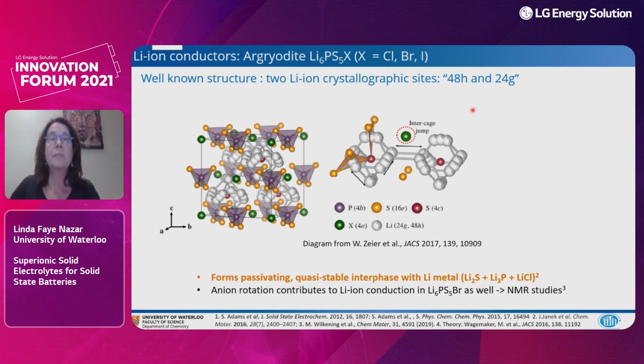And this is a nice cubic structure with PS4 tetrahedra and 2 lithium-ion crystallographic sites, which are known by their Wyckoff notation as 48h and 24g. So these are mostly the 48h sites, and this little transient site in between is the 24g, but almost all of the sites are the 48h. This is almost 98% occupied.